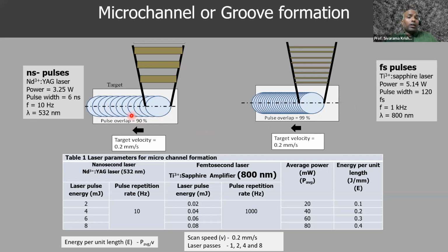Okay, so essentially the grooves are formed because the laser pulses are partly overlapping, and we check this, of course, with optical microscopy, and these grooves tend to get formed, and we varied pulse energies in all cases. It is not that at all times the laser power was 5 watts, it was the maximum power, but the per pulse laser pulse energies that we used in the nanosecond and femtosecond cases were varied to be so. These pulse energies were chosen so that we get similar size of grooves or dimples on the surface of these piston rings.